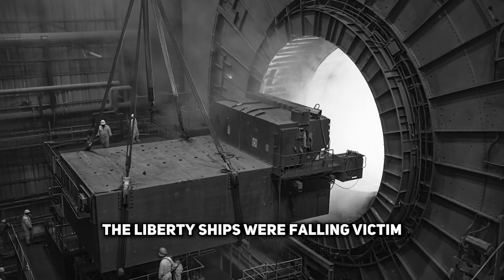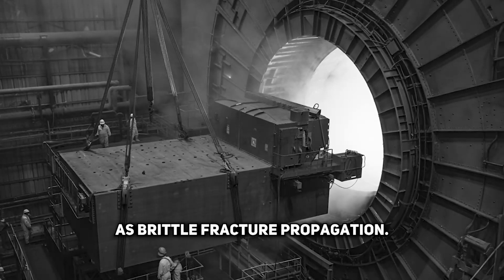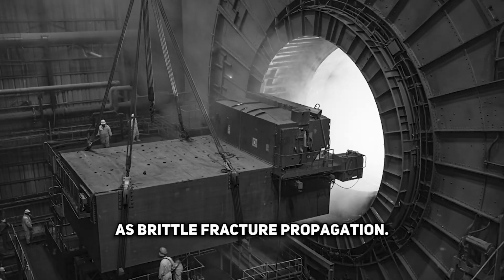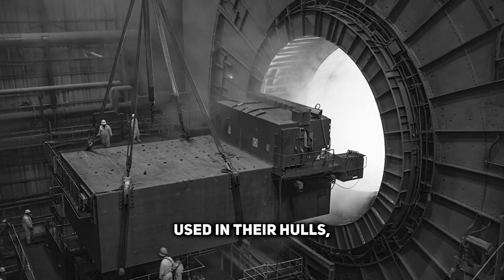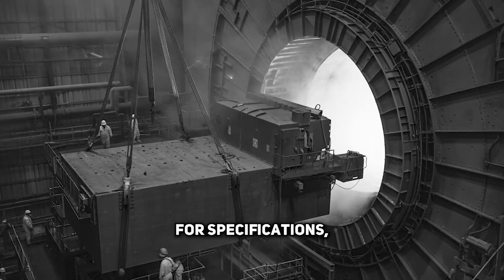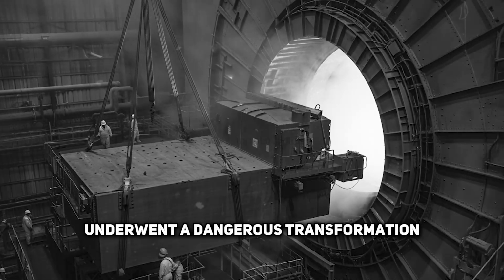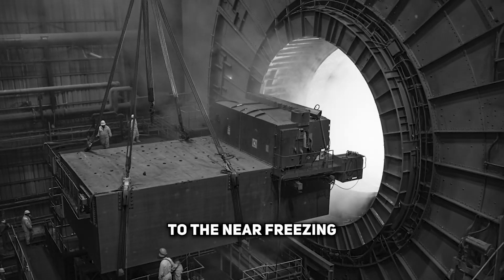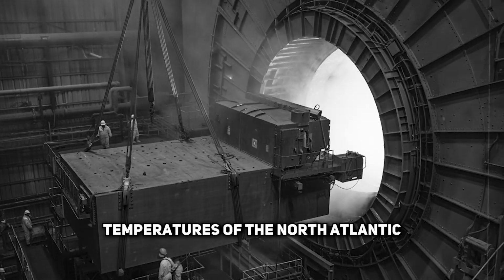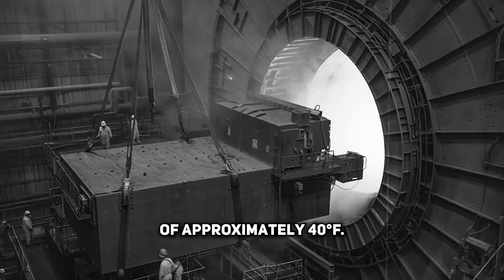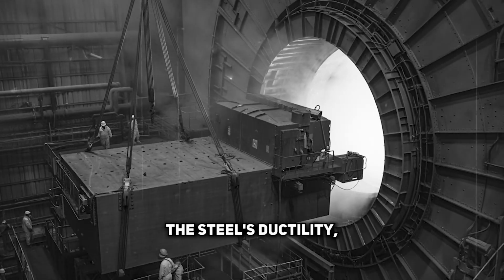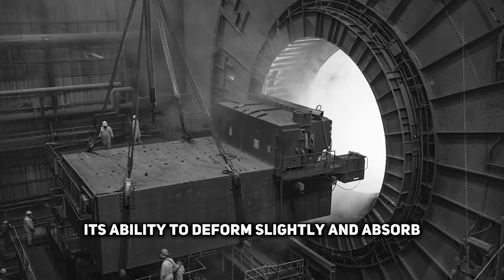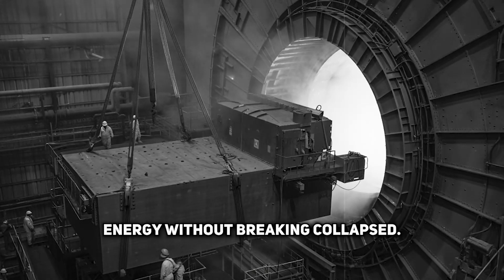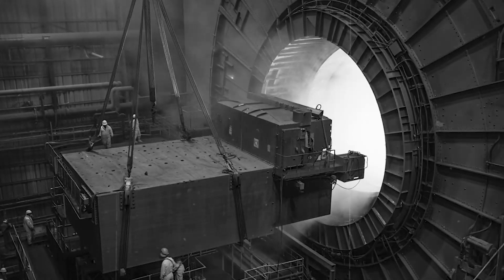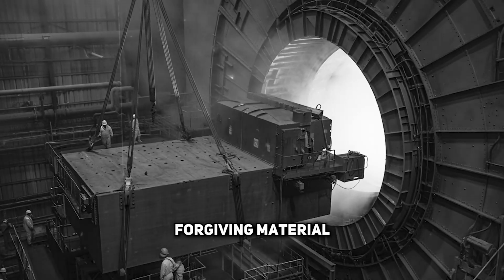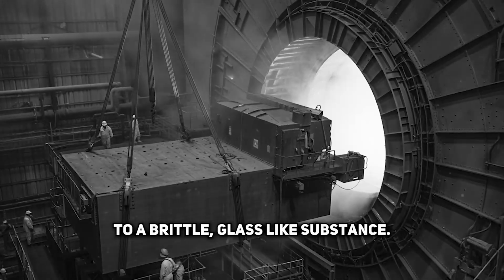The Liberty ships were falling victim to a phenomenon known in metallurgy as brittle fracture propagation. The specific grade of carbon steel used in their hulls, while adequate for specifications, underwent a dangerous transformation when exposed to the near-freezing temperatures of the North Atlantic. Below a critical temperature of approximately 40 degrees Fahrenheit, the steel's ductility, its ability to deform slightly and absorb energy without breaking, collapsed. It changed from a tough, forgiving material to a brittle, glass-like substance.